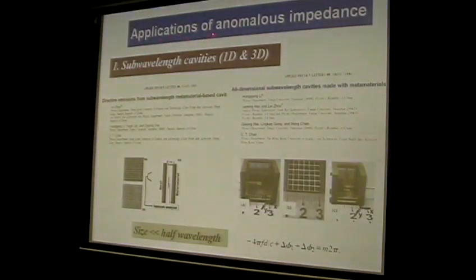There are many applications of such anomalous impedance properties. Let me introduce some of the examples that we have. The first example is that we can fabricate subwavelength cavities. If you look at the condition to form a cavity mode for this cavity, you find this equation is a very famous condition. That means the accumulated propagating wave phase plus the reflection phase at the interface, the sum of this should be a multiple of 2 pi.